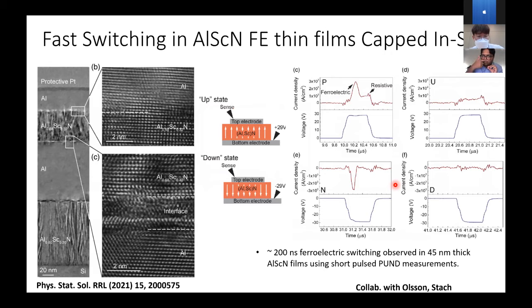Final question that I want to mention is about switching. A lot of people are interested in switching speeds. So we have actually done switching speed measurements, and we have seen about 200 nanosecond switching. Switching has been observed using PUND measurements. PUND stands for positive up, negative down measurements. In this case, we send a fast pulse through the ferroelectric, and we measure the current flowing out as a function of time. And we see that this ferroelectric current peak is about 200 nanoseconds in width, and therefore we conclude it's about 200 nanosecond switching.